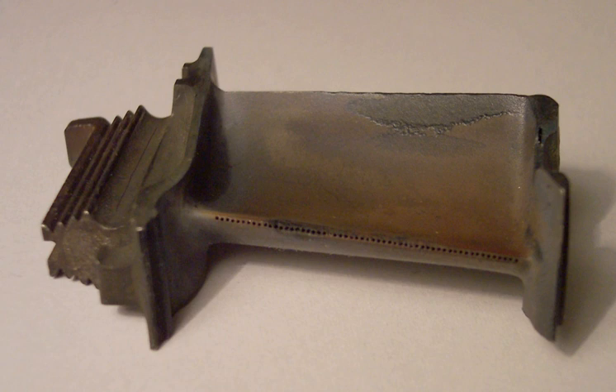Topic: There are various degradation mechanisms for thermal barrier coating, and some or all of these must operate before failure finally occurs. Oxidation at the interface of thermal barrier coating and underlying bond coat. The depletion of aluminum in bond coat due to oxidation and diffusion with substrate. Thermal stresses from mismatch in thermal expansion coefficient and growth stress due to the formation of thermally grown oxide layer. Imperfections near thermally grown oxide layer. Various other complicating factors during engine operation. Additionally, TBC life is very dependent upon the combination of materials, substrate, bond coat, ceramic, and processes, EBPVD, plasma spraying, used.